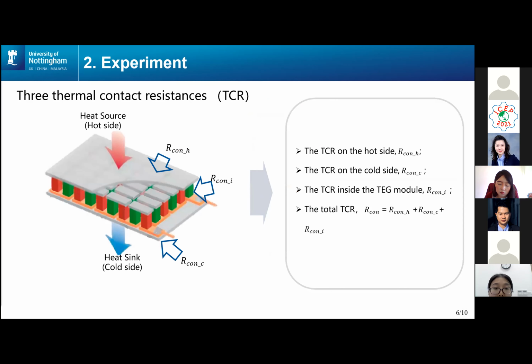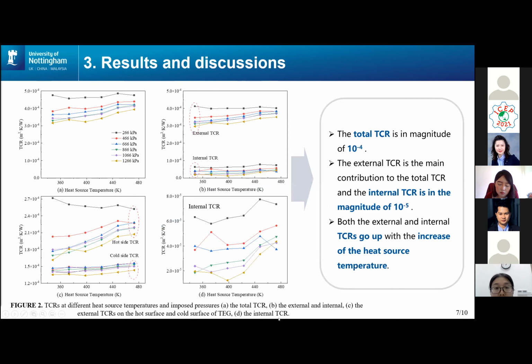With our test rig, 3 different thermal contact resistances at different locations in the system are measured. That includes the thermal contact resistance on the hot side, on the cold side, and inside the module. The total thermal contact resistance is the sum of the 3. The experiment reviews the impact of the heat source temperature and the load pressure on the TCR respectively.